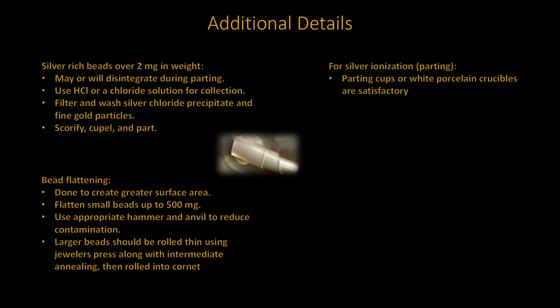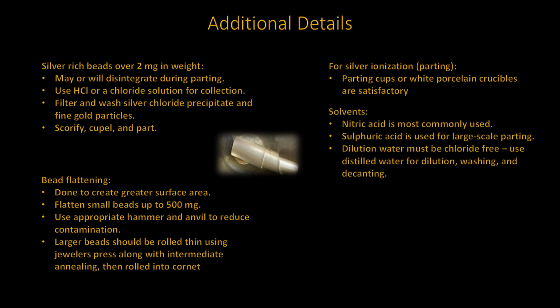For the parting process, parting cups are most commonly used. However, porcelain crucibles can be used satisfactorily as well. Nitric acid is mostly used as the solvent, but sulfuric acid is used for large-scale parting. The important thing to remember is to use distilled water for dilution, washing, and so on. The water must be chloride-free. The chloride will contaminate the gold with silver chloride, and if the chloride concentration is large enough, it will aid in the dissolution of some of the gold.